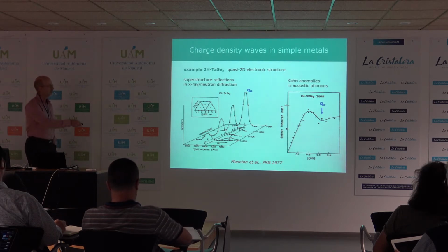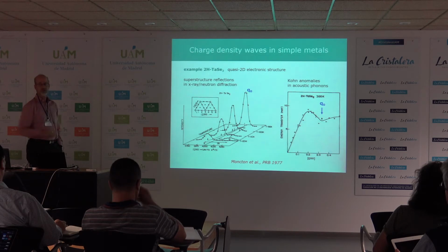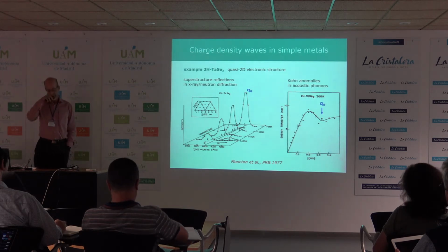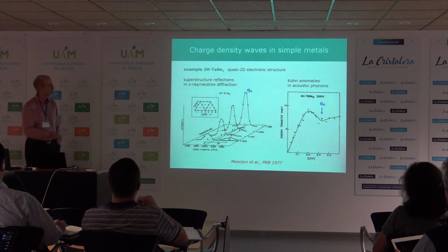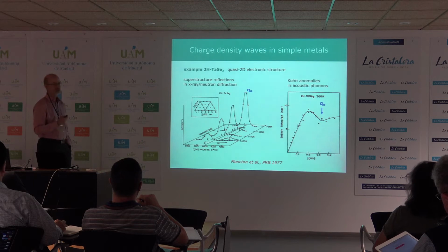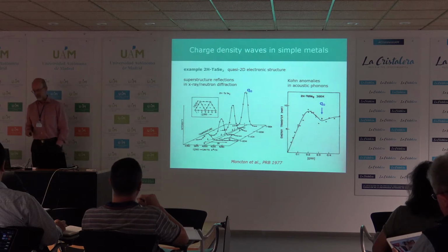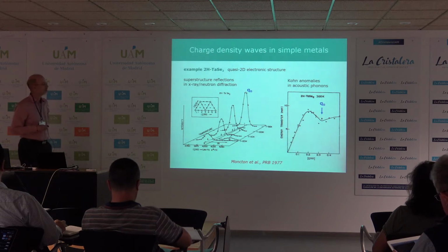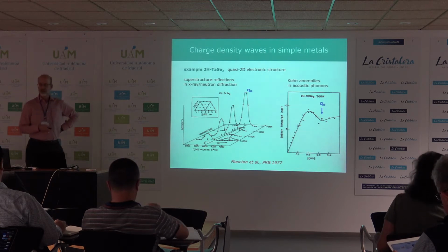And he also studied phonons, and this is one particular acoustic phonon branch where you see a prominent anomaly at the charge density wave vector. Actually, this anomaly happens even at room temperature, much above the actual three-dimensional charge density wave transition, as you might expect in a low-dimensional material. Okay, so this is sort of ancient history.